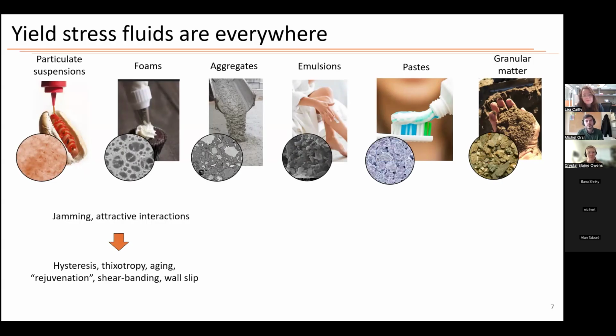And these interparticle interactions lead to the time-dependent effects that we see and that we're frustrated by and that we're so interested in studying, like hysteresis, thixotropy, aging, shear banding, wall slip. And ketchup, I already said, experiences some thixotropy that we're mostly ignoring right now, and also aging and wall slip, which we'll be talking about more.